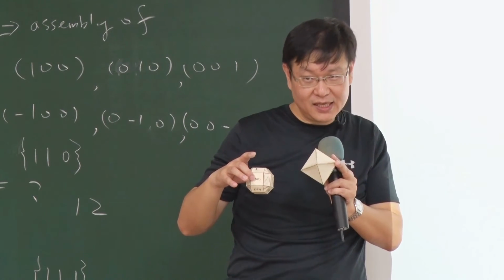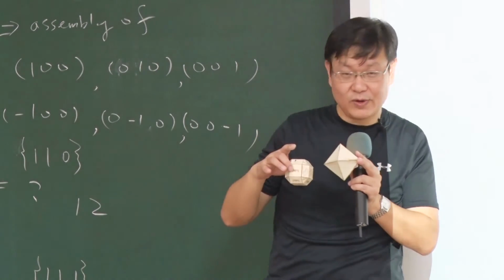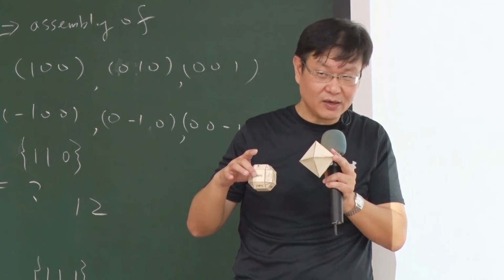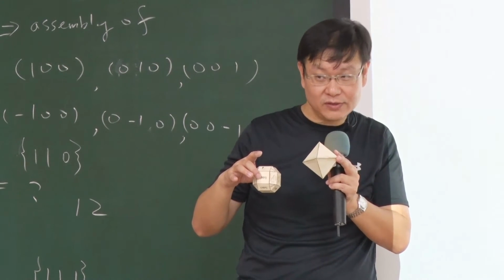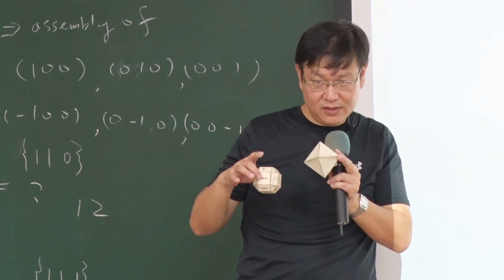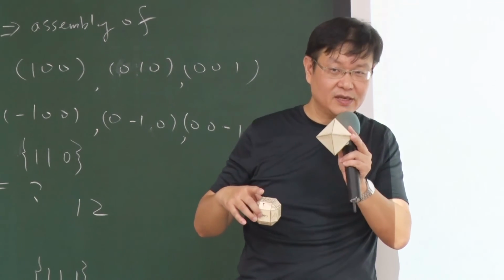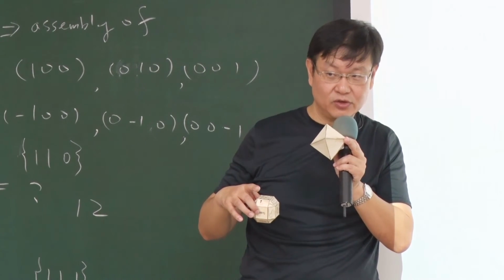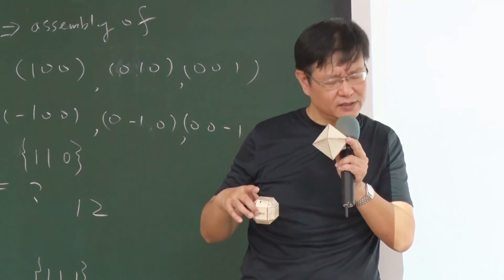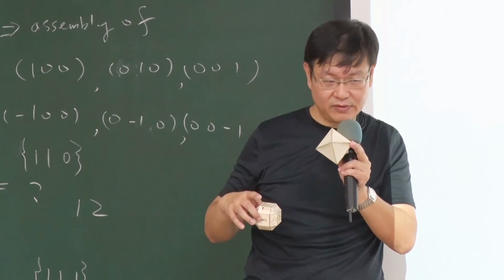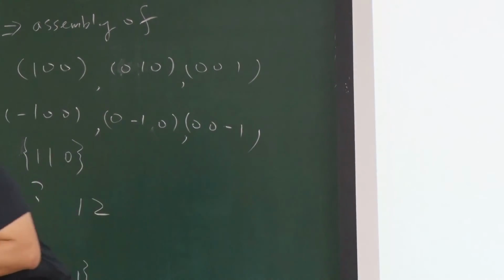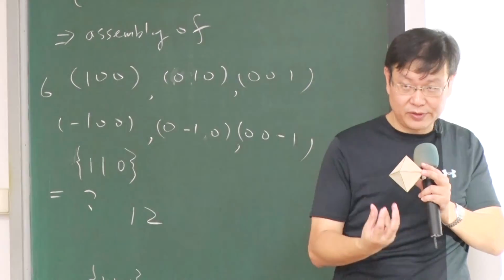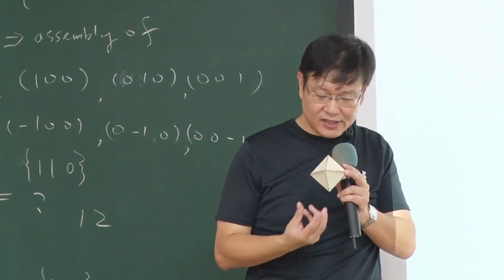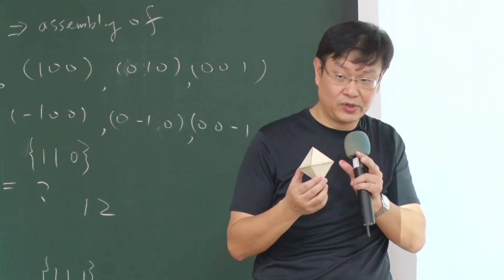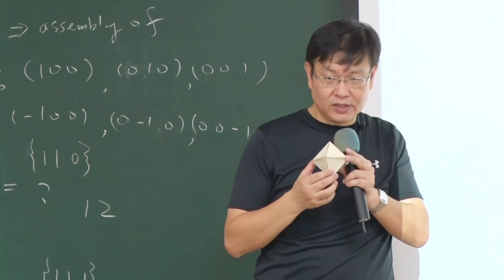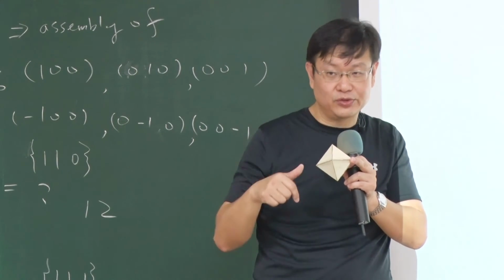Okay. Can you figure it out? So we have 6 100 surfaces, 12 110 surfaces, and 8 111 surfaces. We connect all the 111 surfaces and it becomes the 8-surface cube here. Why is this important? Because when you look into the etching results, all the etching results stop at this kind of cubic structure. The difference is which direction you look from.